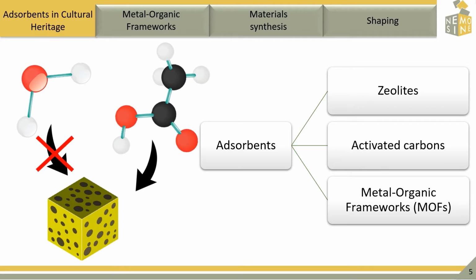Activated carbons are also considered for these applications. However, they emit dust that can damage further the artifacts, and they are usually characterized by low affinity with certain gaseous molecules. Thus, metal organic frameworks have emerged as an interesting alternative since their structure can be easily modulated to the restrictions, increasing the affinity with acetic acid while decreasing the affinity with water. In addition, these materials present higher pore size than zeolites, being advantageous for the adsorption of gaseous molecules.